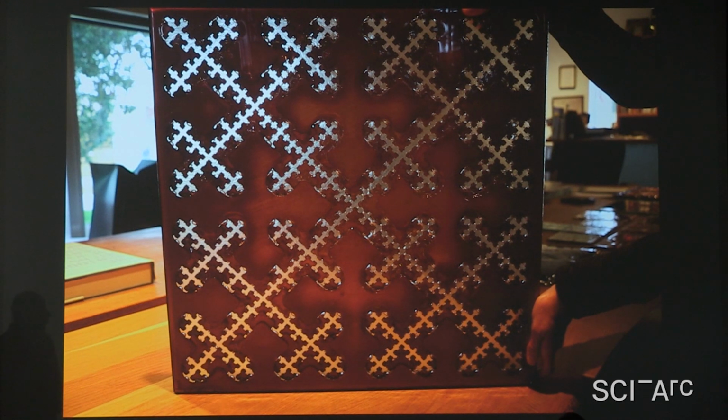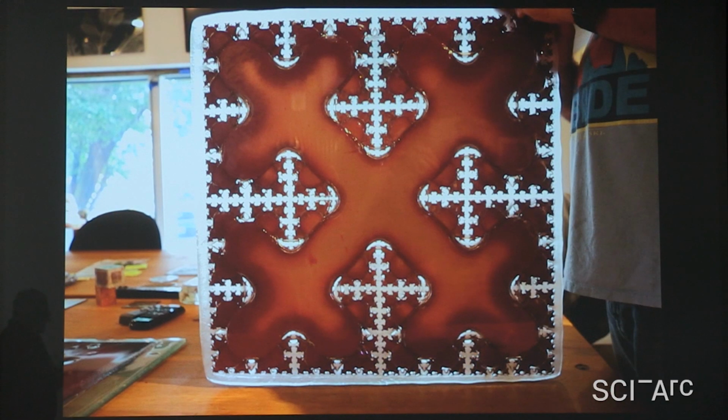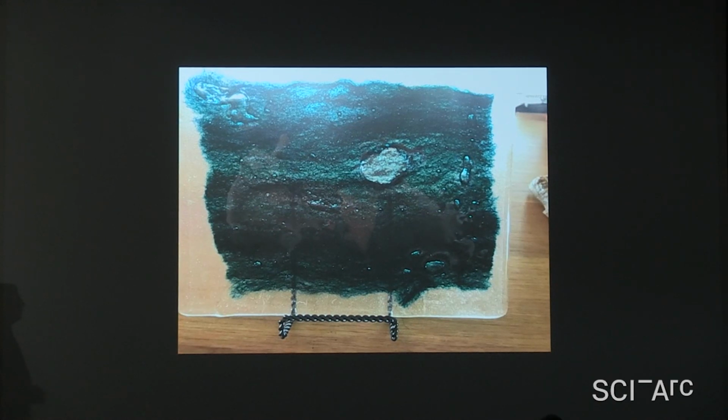Here, then, we've taken and slumped it. We've taken 7 layers of glass, 6 layers of copper, layered them up, and these images don't really show you, but by taking that, you can get this really interesting depth effect with slumped glass fused with metal. So the thing is relatively thick, relatively heavy, but the effect was quite amazing. Here's where we just simply took copper wool of a different alloy and slumped it between 2 pieces of glass. Kind of came out like again, the picture doesn't show the color that comes out of this and the depth of the color.